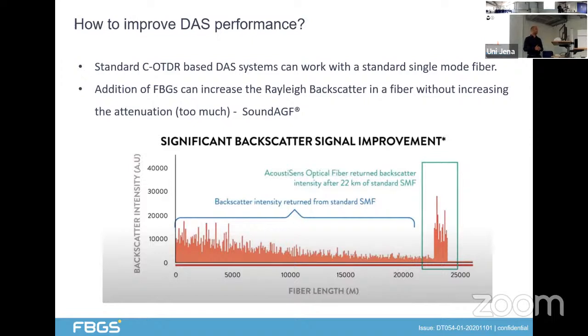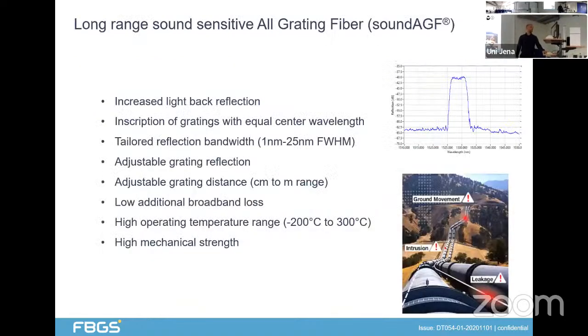If we bring in a fiber at the end which has an increased Rayleigh backscatter, that's the green part where you can see you can increase the signal. And this principle can also be used by using gratings. If we write gratings with a very low reflection in the fiber, they do the same. They just increase the reflection. Also, we don't have the scattering effect. We have direct reflection back to the source.